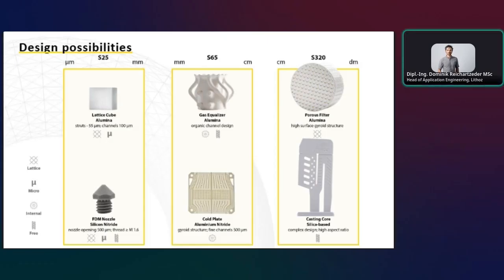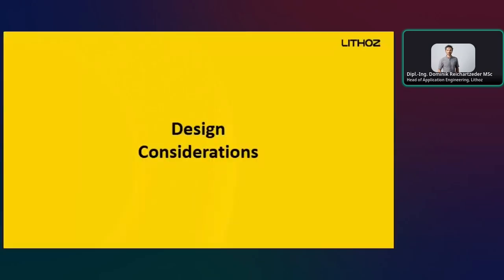On the bottom, you can see aluminum nitride cooling plate with intricate cooling channels and lattices, which shows what is possible to produce inside a part. On the bottom left, we can see that also threads are possible in this silicon nitride nozzle. Knowing what's possible is equally important as knowing what is not and what to consider when designing for ceramics.